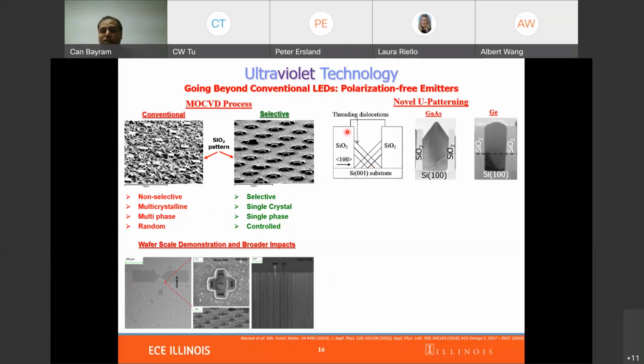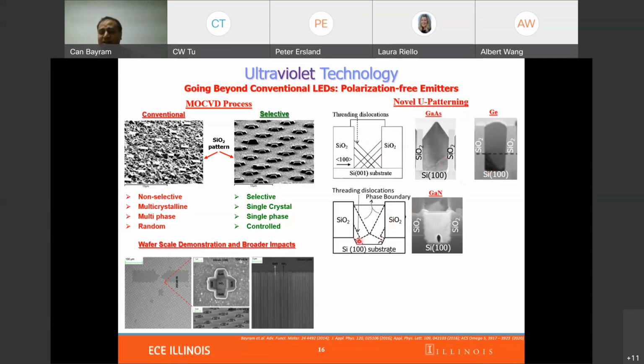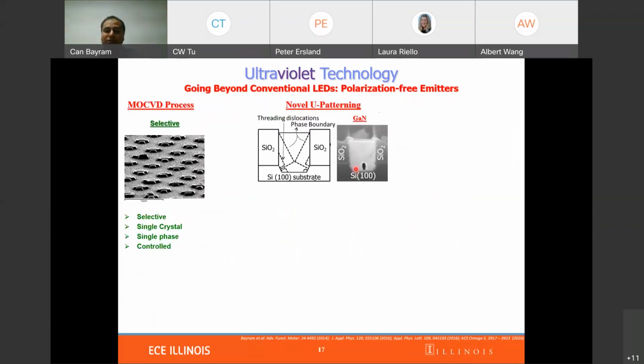Now the aspect ratio trapping structure shown here is commonly used for the arsenide, phosphide, and germanium family. Mainly you have silicon dioxide sidewalls on top of a silicon 100 substrate, and the defects follow the growth direction and they get terminated. Basically they get stuck in the sidewall and the top layer is defect free. Here you can see how defects are localized to the bottom of this aspect ratio trapping structure. Now what's interesting is if we pattern this substrate to make what we call a U groove, exposing silicon 111 facets, we have a different type of defect formation, and we notice that we have a material change after these facets meet. So let's look into this in more detail.